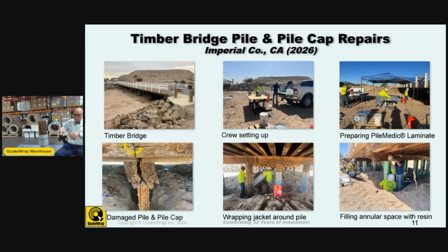The top 2 pictures on the right show how small the footprint of the crew is. They basically had everything on the back of a pickup truck and set up a tent to shield them from the heat of Yuma and the southeastern California deserts. On the lower pictures, you see that the pile has been wrapped. In this case, we used some 1-inch spacers around the pile and wrapped the jacket around it to create that 1-inch annular space. On the lower right photo, you see that they are pouring the mixed epoxy grout into the annular space.